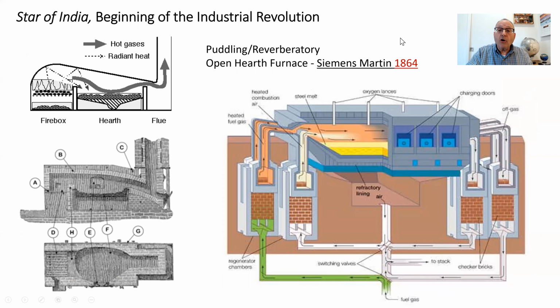So here's the open hearth process, or the puddling process. Initially, what they found is that if they built a fire and they had this big reflecting surface, and the heat could come up here and they have air flowing across this large, shallow pool of molten cast iron or iron, they could remove a lot of this carbon and go up the stack as CO2. It was a long process. It took quite a while, and they developed these really big brick furnaces. These were probably 3-4 times the size of your living room, huge furnaces.